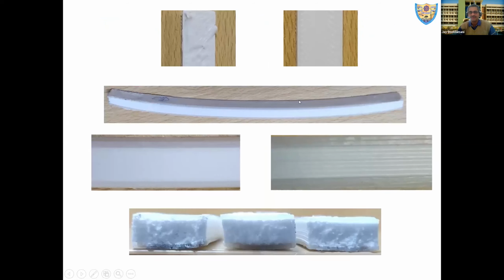Recently, we ventured into 3D printing of sandwiches with syntactic foam core. And this printing is done in one go. And it is done in situ, wherein we established seamless bonding between the skin and the core, which is generally not available in conventional manufacturing methodologies, wherein we manufacture core and skin separately and then bond them together. We also printed some curved sandwich panels as well.